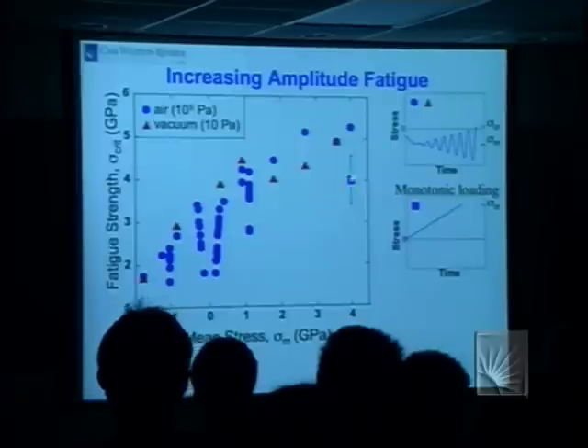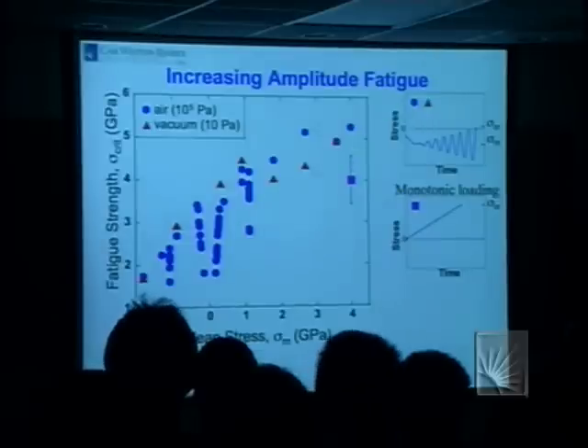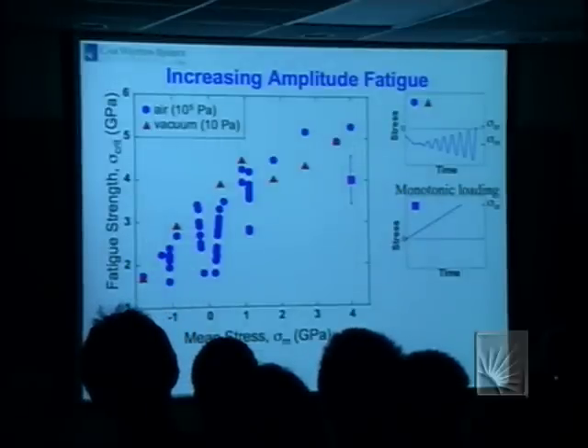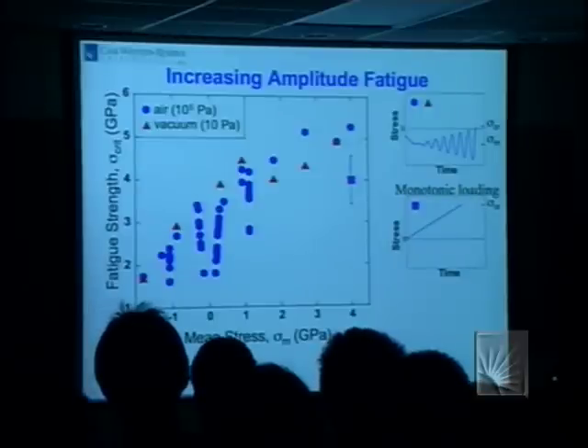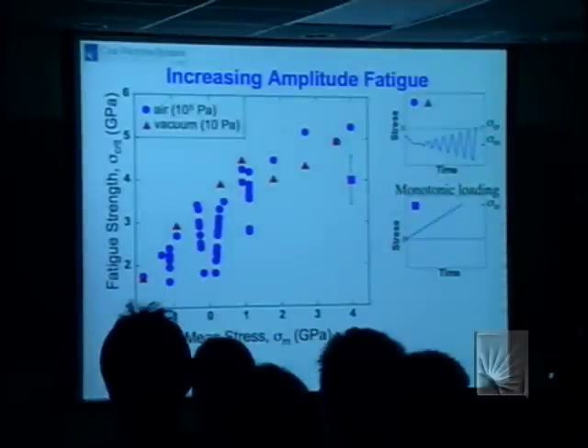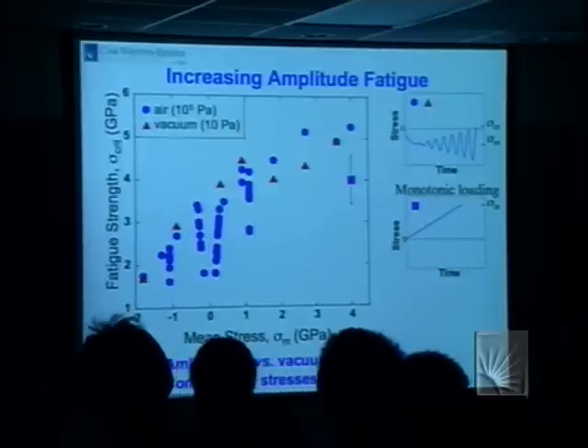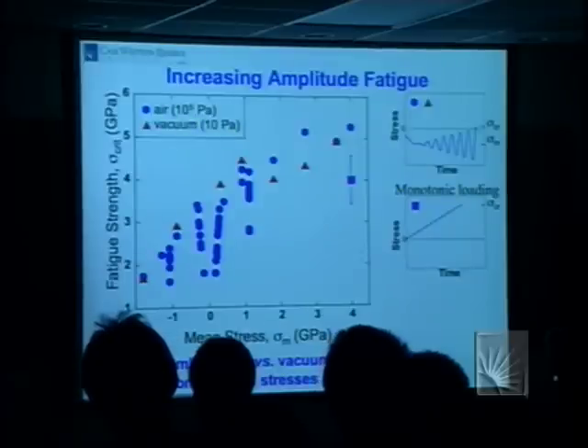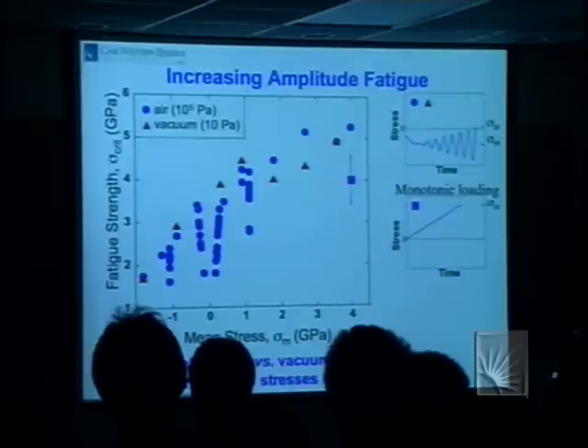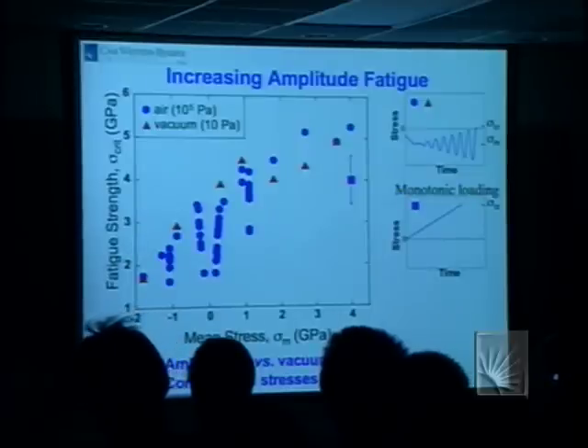When we compare this with monotonic loading, that's the value of the monotonic stress, about 4 GPa, you see there's a dramatic weakening with large negative mean stresses. And our interpretation is that there must be asperities on the sample surface, and we're driving two asperities together, causing some mechanical damage. And this is not sensitive to environment. I've shown some experiments in air and at 10 pascals pressure. And contrary to lots of people's intuition, compressive stresses can be very damaging. We normally think compressive stresses in brittle materials are good because they fail under tension. This is an example of high cycle fatigue with mean stresses where it's not so good.